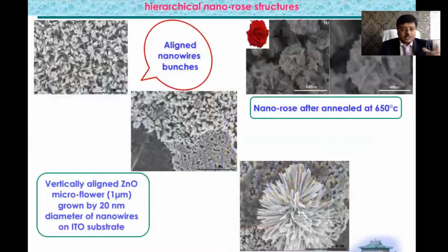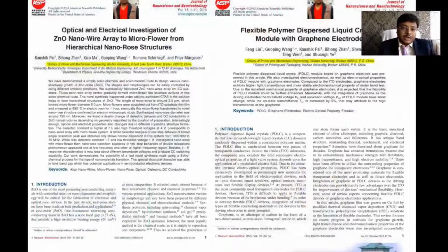In this technology, you can see the FESEM structure is a vertically aligned zinc oxide microflower structure. It is a bunch of nanowires, gradually formed. You can see here it is gradually formed. This is a microflower after annealing, and at 650 degrees centigrade a nano rose-like structure evolved. This series of work we published with American Scientific Publishers, and for this flexible polymer dispersed liquid crystal module with graphene electrodes, we made it with the same procedure.